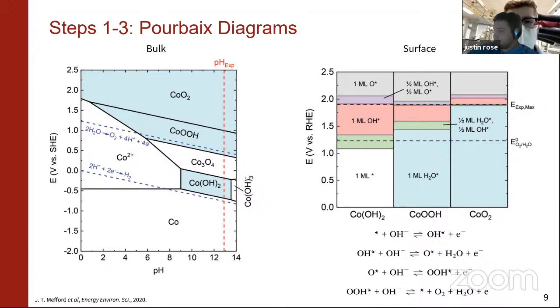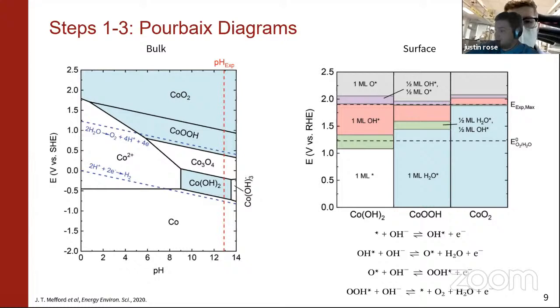They considered a few coverage conditions: a monolayer of nothing, water, OH*, or O*, or a half-monolayer of one species and half-monolayer of another. This calculation is quite computationally demanding, so they decided not to simulate smooth transitions between monolayers, reasoning that a half-monolayer of each is sufficient to represent a transition between two coverage conditions. I'll include the reaction scheme at the bottom whenever I can, since I found myself flipping back and forth to remember which reactions we were considering.